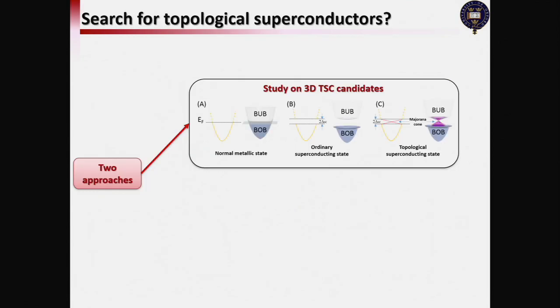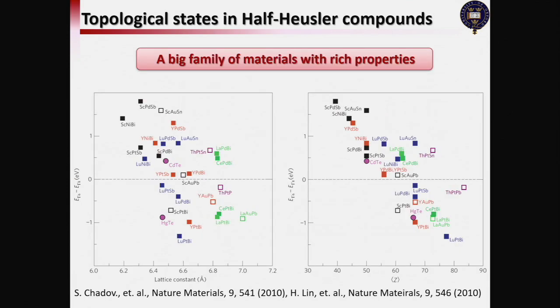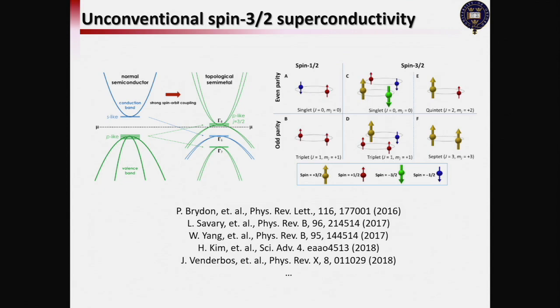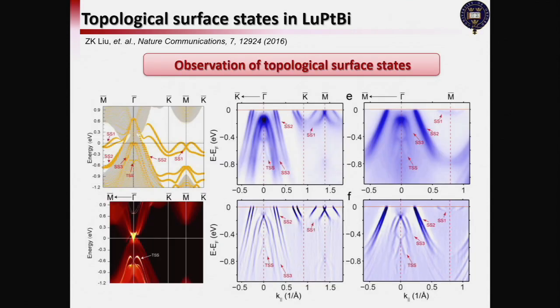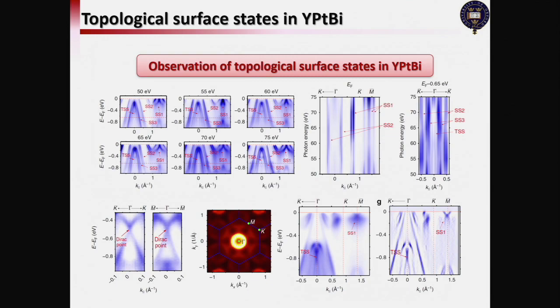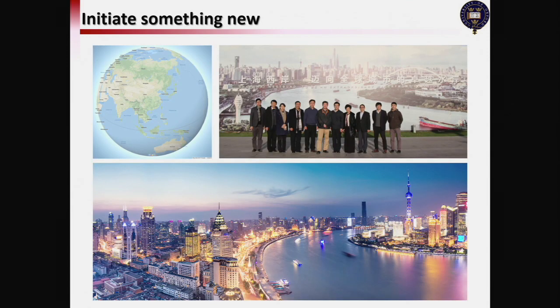So I think I'll skip this part on topological superconductors. Basically, we found this candidate in the Heusler compounds, the lutetium platinum bismuth and yttrium platinum bismuth. So we show that they host the topological surface state, even though the topological surface state is buried inside the bulk state, so it has a strong hybridization, yet the robustness of the surface state may be stronger than we thought.